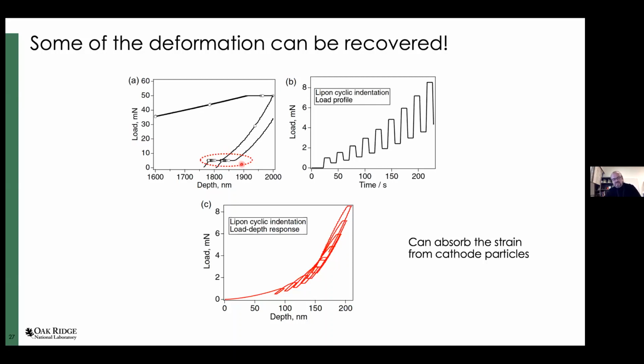So what this tells us is that LiPON somehow can restore deformation with time. It has this creep-like time-dependent behavior when you unload it, and it restores the deformation. Most likely it's the densification that gets restored, because restoration of that shear pileup is simple and feasible.